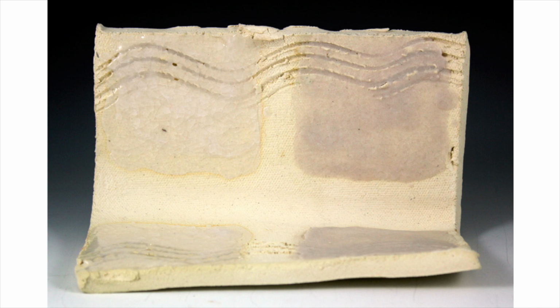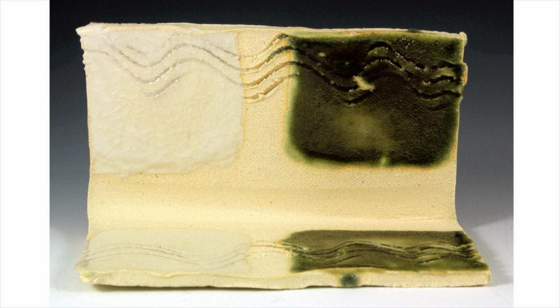Feldspar makes a glaze all by itself, but is not totally wonderful. This is nepheline syenite on the left and Custer feldspar on the right, fired to cone 6 in an electric kiln. This is nepheline syenite with 2% copper carbonate added just to see the results a little more easily in my tests.